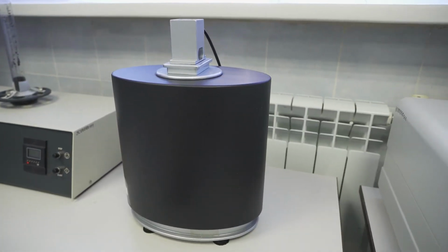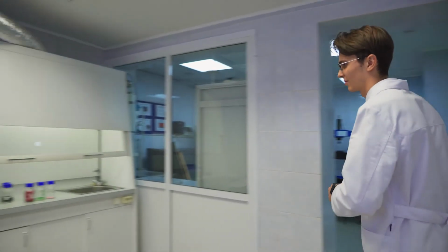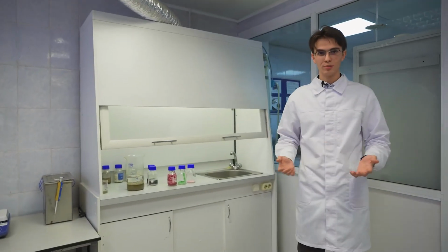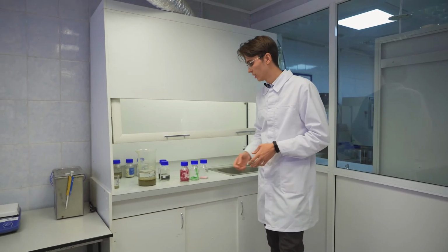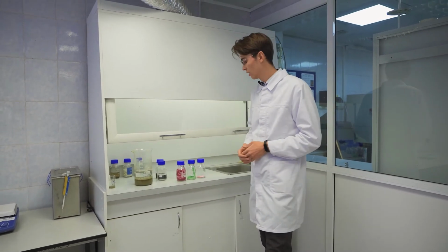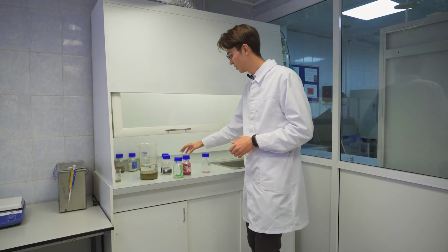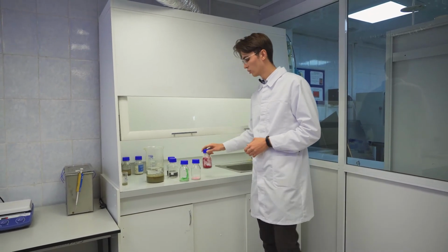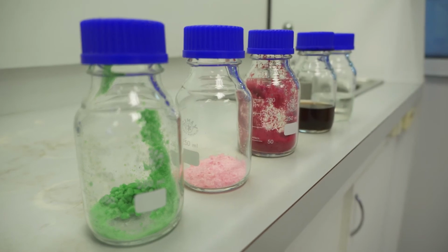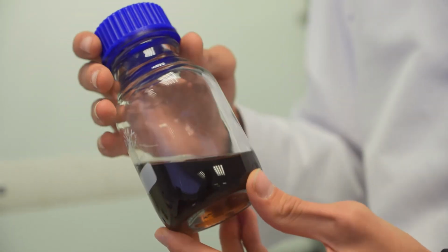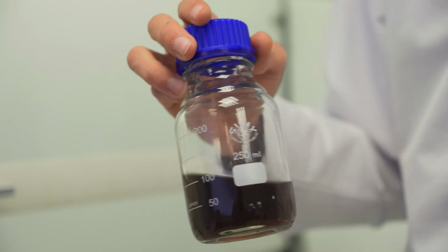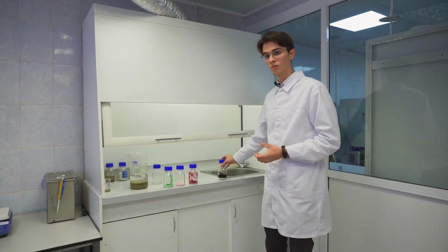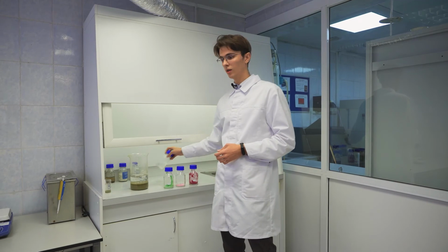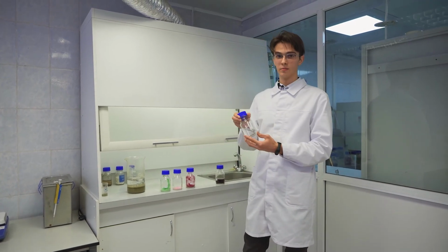We have to get the material to analyze it. Now we are going where we can get it. Here we are. So, here you can see salts of three chlorides, notably salt of nickel, manganese and cobalt. We dissolve them, and we get a brown-colored solution like this. Then we dissolve the lithium hydroxide separately, and then add it to this solution.